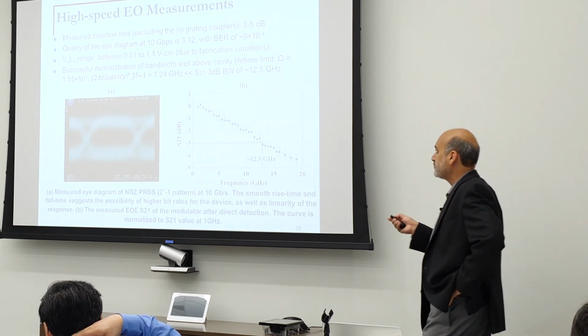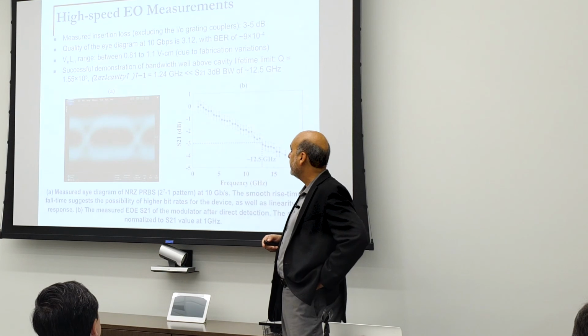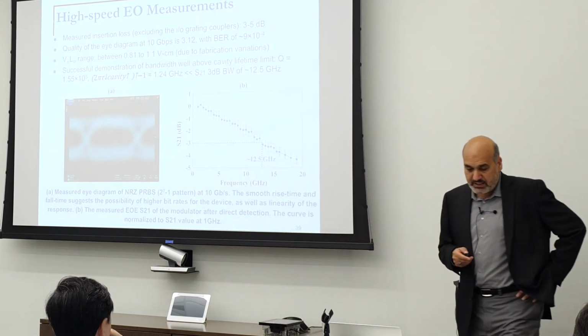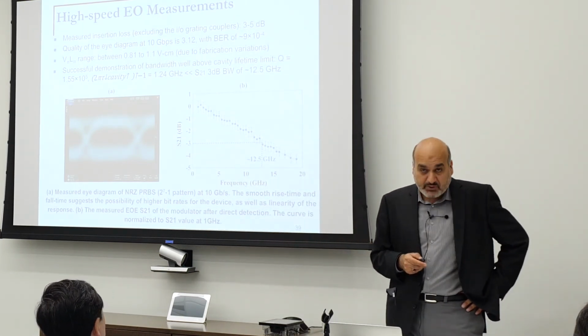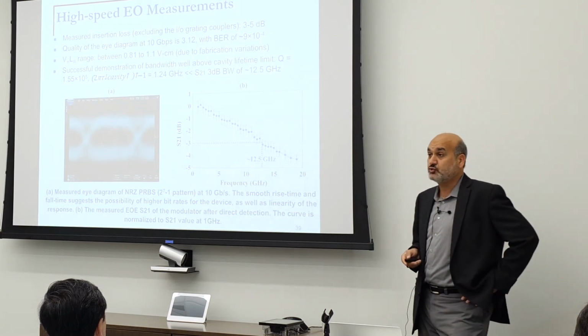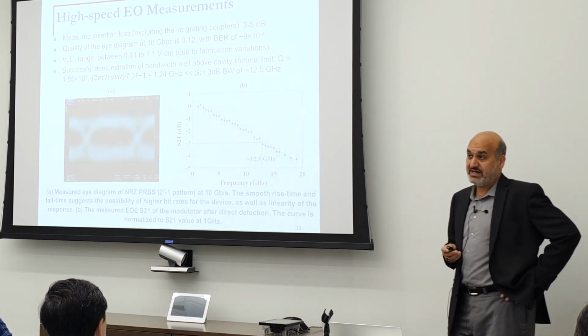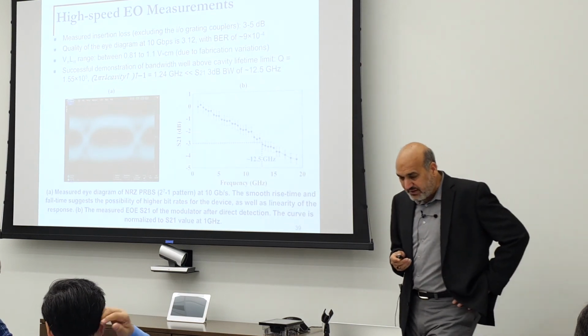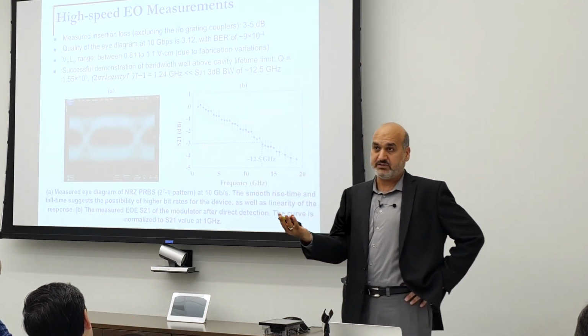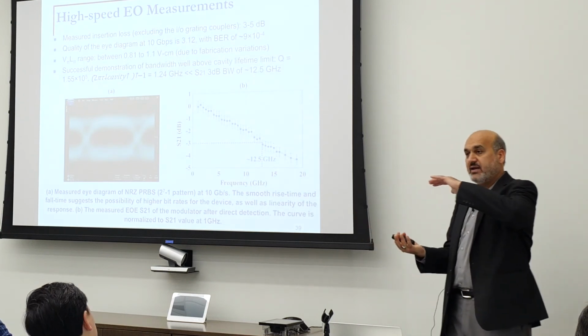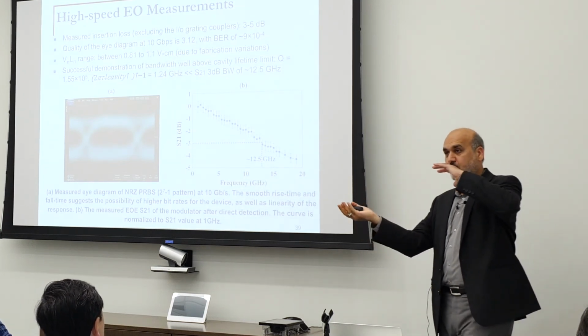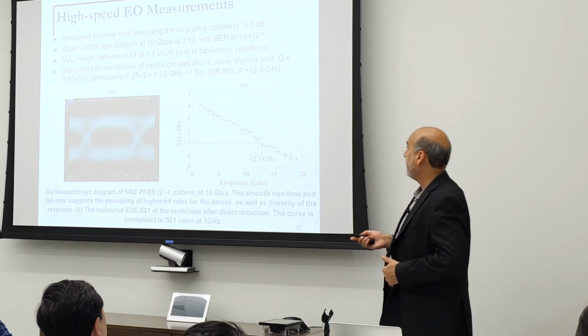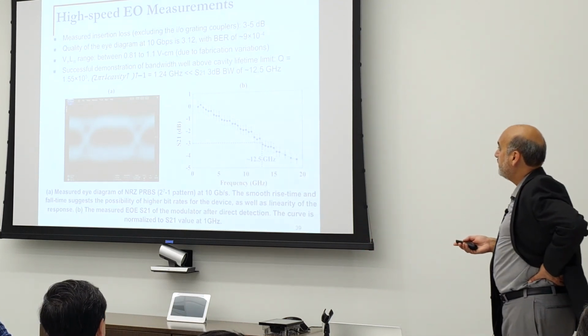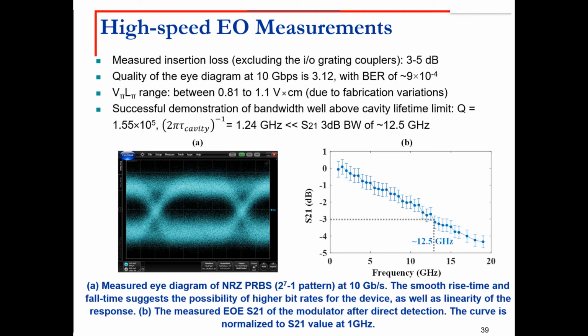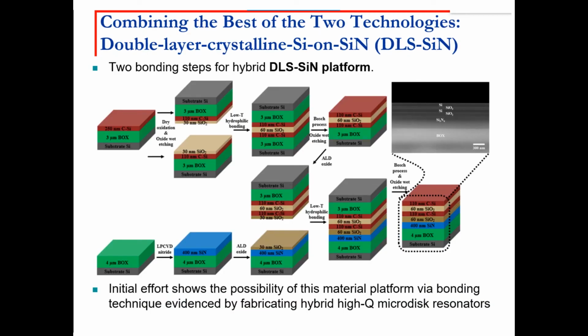So that type of structure is now being worked on getting into 60 gigabit per second at a few femtojoule per bit power consumption. And that's the direct result of using a hybrid material that allows me to combine a very high Q device or very low loss material with an integrable material. Now, in the rest of the slides, I just show you quickly where we go from here.